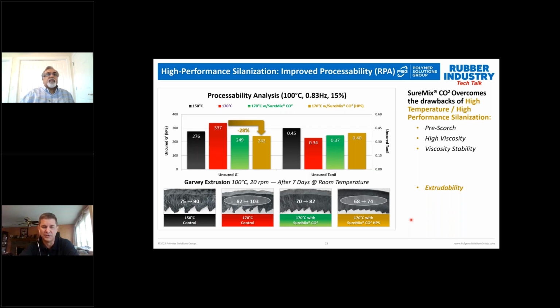So in the case of the 170 degrees C compound, 82 was the compound viscosity as mixed, and an increase to 103 after 7 days storage at room temperature. The compounds containing SureMix maintain viscosities down in the 70s, very close to the 150 degrees C silanization control. So here we're able to utilize SureMix CO2 to get 20 more degrees of silanization temperature, which is going to drive the dispersion of the silica dramatically to improve the properties. And we're still able to process it. So let's take a look at the properties.